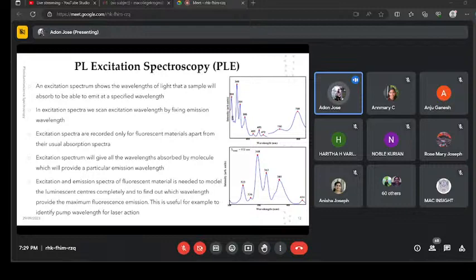So based on that emission wavelength only, we can record the excitation spectra. Based on the intensity of the excitation bands, we can identify at which excitation wavelength we can observe the luminescence behavior from a luminescent material. Actually, the excitation spectrum usually refers to the range of wavelengths of light that are absorbed by a substance, causing its electrons to transition from a lower energy state to a higher energy state. It is similar to an absorption spectrum. We already discussed that. But the excitation spectrum is recorded by scanning the excitation monochromator through different wavelengths while monitoring the emission at a fixed wavelength.